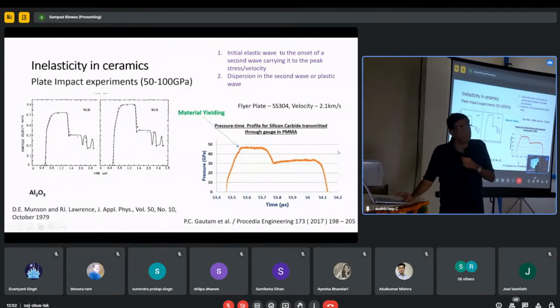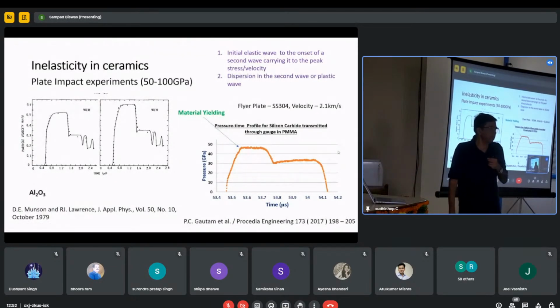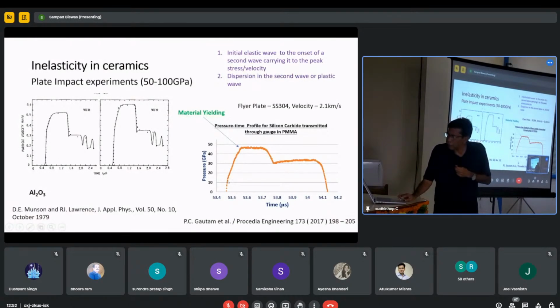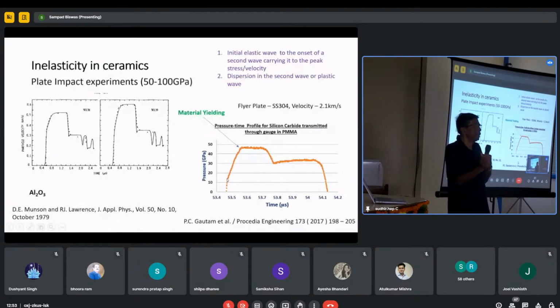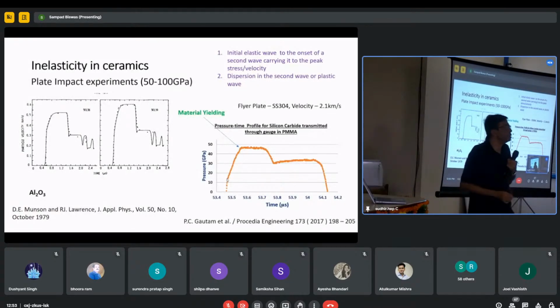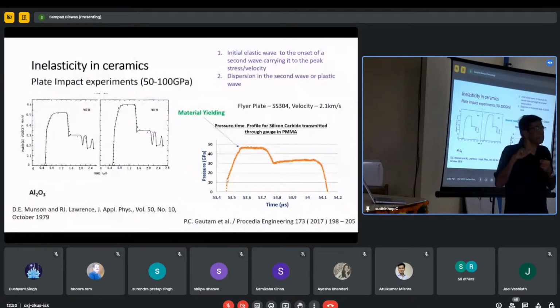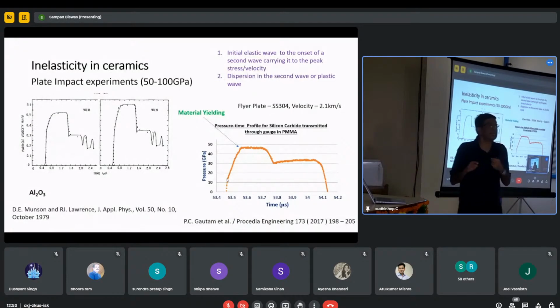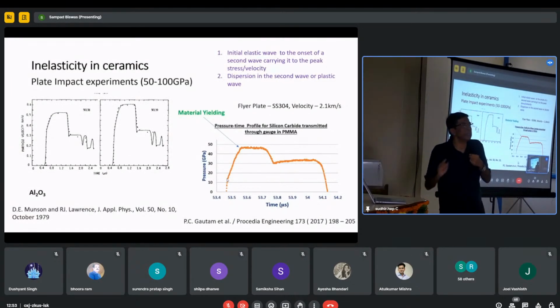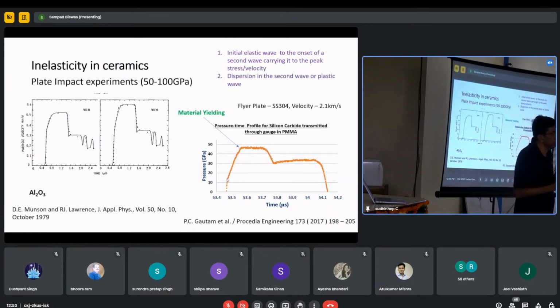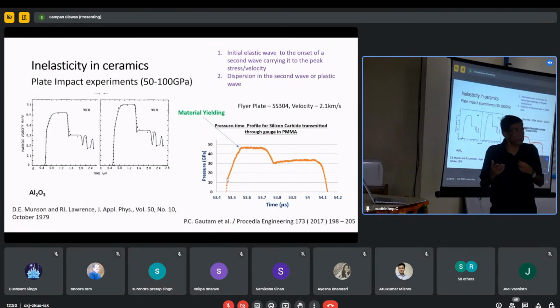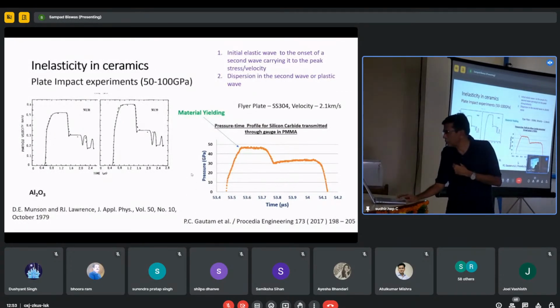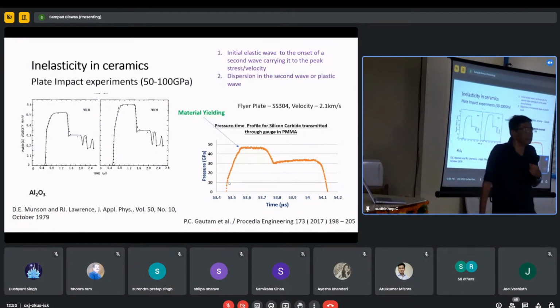Our samples, one sample's data I am showing now. You see, the inelasticity comes from this level. When it starts deviating from the linear elastic mode, this point is called the elastic limit, named after the scientist who discovered this, the Hugoniot elastic limit, or HEL. So the Hugoniot elastic limit is a parameter by which we can judge ceramics from one to the other, which is very effective. The Hugoniot elastic limit here is very high, about 13 GPa, which we have found in the case of silicon carbide.